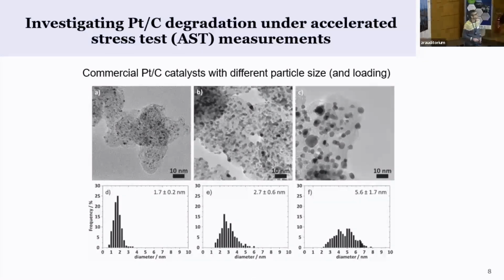And if you now look at commercial catalysts, and these are no alloys, so simple platinum nanoparticles on carbon supports, with a certain ratio of platinum to carbon. What you see here are different sizes of the nanoparticles. One with rather small particles, one with an intermediate size, and one where they tempered the catalyst to get a little bit larger particles, ranging from 2 nanometer to around 5 to 6 nanometer.